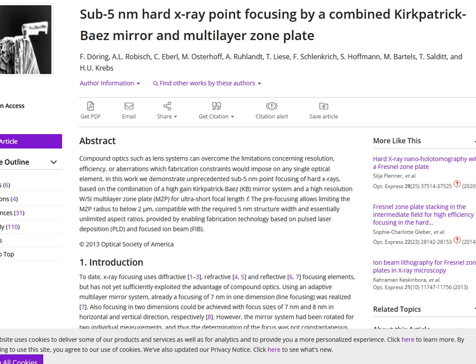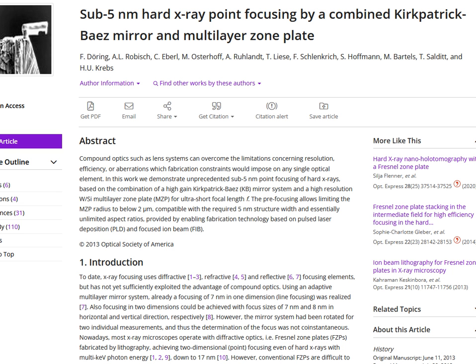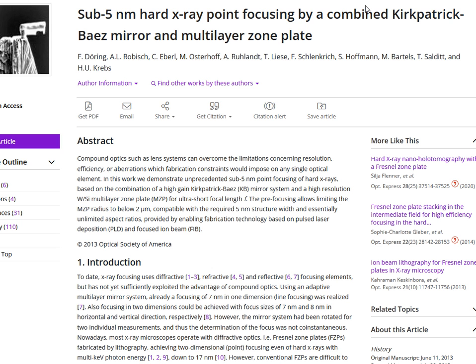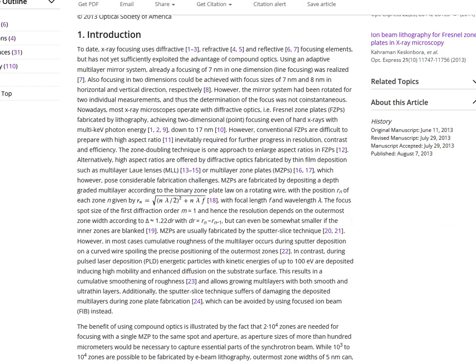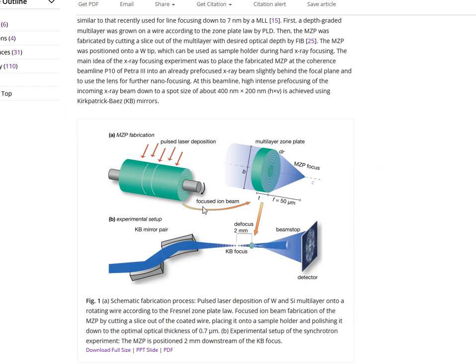And last but not least, here an example for the multilayer deposition that was done in chamber number 3. This is a collaboration of the Institute of Materials Physics and the Institute of X-ray Physics. Here we deposited by pulsed laser deposition a multilayer zone plate as an X-ray optic. I will show you the procedure here. On a rotating wire the PLD was performed, and here we have the material system, tungsten and silicon, that was alternately deposited on that wire.